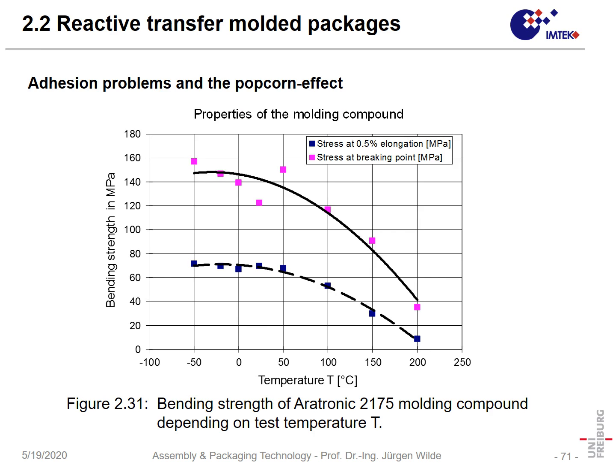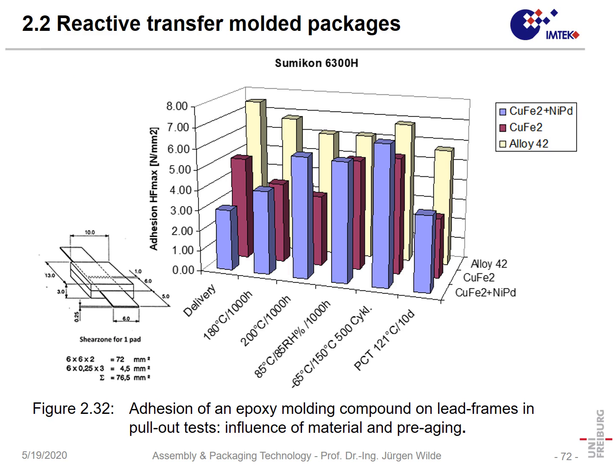So moisture is a problem, and moisture can degrade adhesion. On the other hand, it is also a good point to think about adhesion in systems where we have polymers, and in the polymers, for instance, a lead frame of copper is embedded. And here we made a certain test. The sample can be seen here. We pull in this direction because this strip in the middle is sectioned. Both strips can be pulled apart, and what we measure is the adhesion on these layers here.